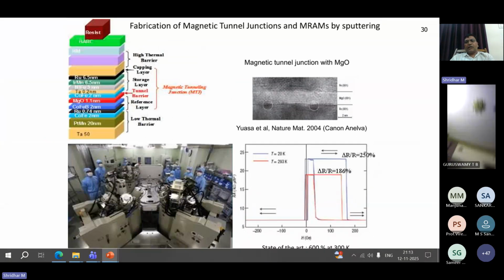Yeah, these are the heterostructures I just mentioned. Actually, these are the heterostructures, where you deposit layer by layer. Assume that this is tantalum and this is platinum of 20 nanometer. If this thickness is increased to 21 nanometer, the entire device property is going to change. Okay. So controlled deposition and controlled nanofabrication technique is highly important in semiconductor fabrication.